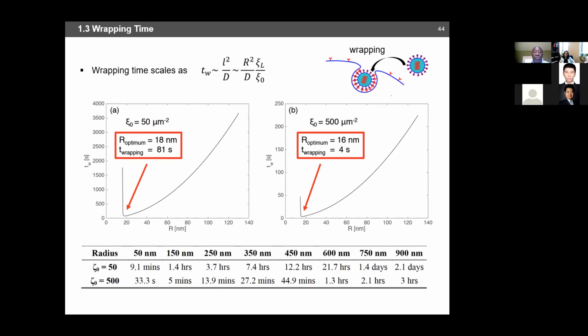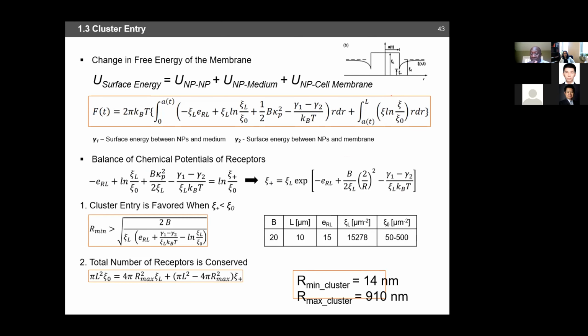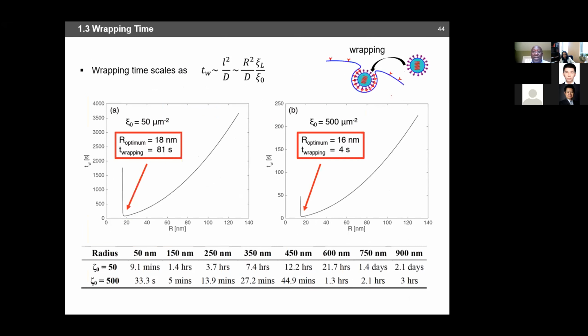And so with this, you can now determine the minimum size of a cluster that can enter to be about 14 nanometers, and the maximum size to be about 910 nanometers, which is consistent with experiments. And then one can think about the kinetics of the wrapping time as you encapsulate the nanoparticles, and think about the diffusion of the receptors into the encapsulation process.